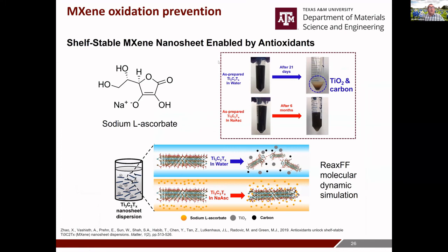So when we look at sodium ascorbate, for example, these are the results as prepared in water, the initial colloids, and after 21 days we can see complete degradation, while with ascorbate they still look pretty good, dispersed nicely and dark black. Also MD modeling shows that sodium ascorbate has a tendency of arranging around the nanosheets, shielding them from degradation and oxidation.